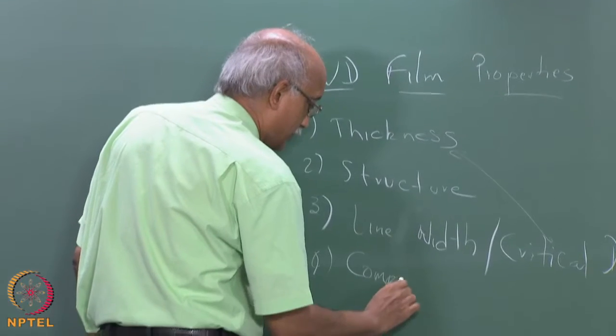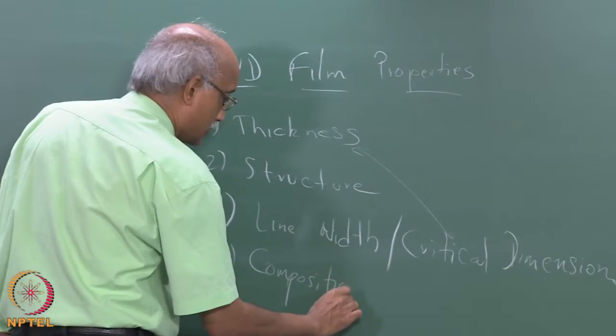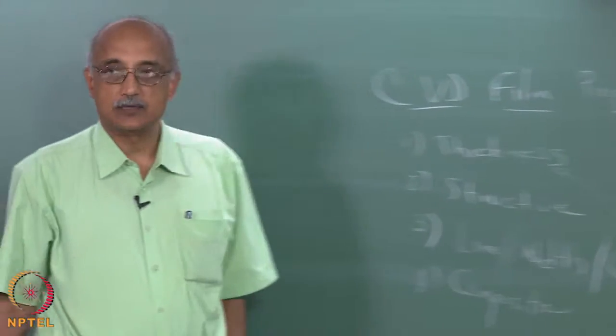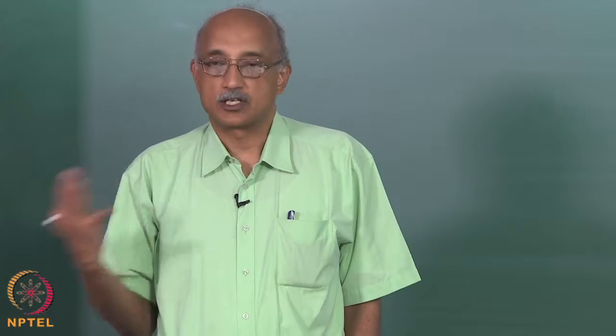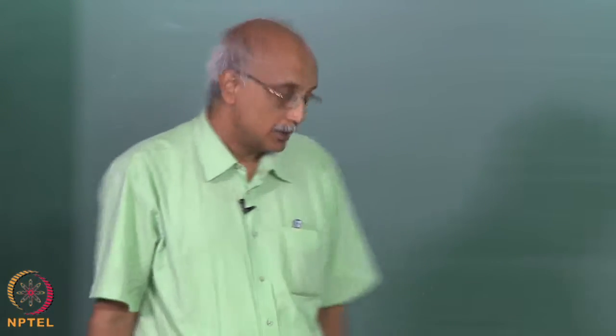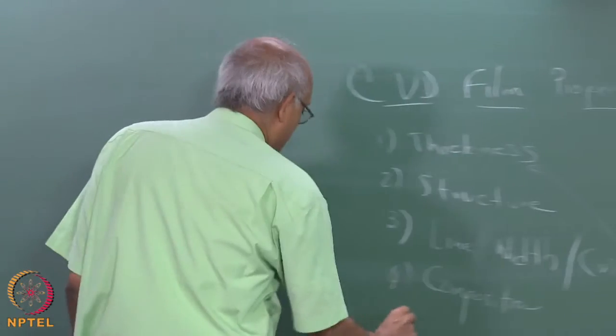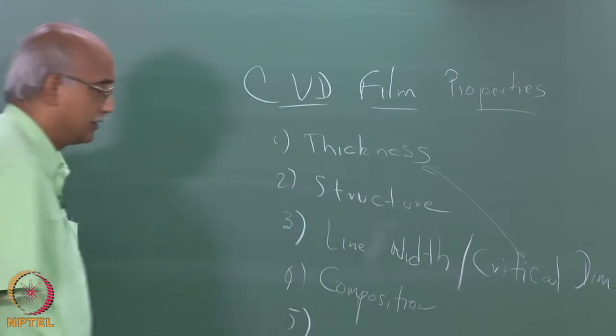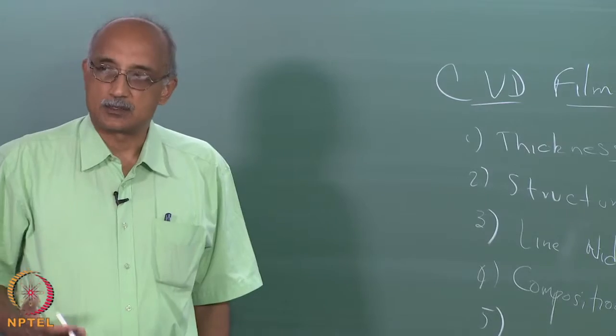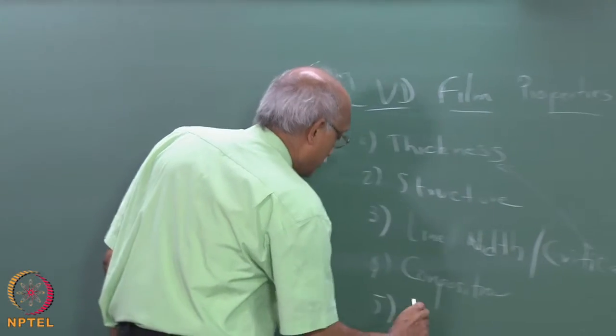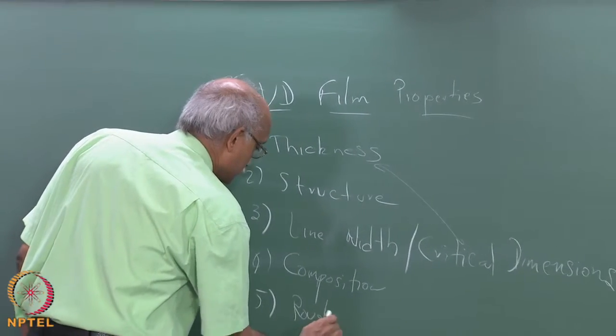Composition is obviously very, very important to know. You are trying to deposit a certain CVD film, you have to be sure that that is what you are depositing and that it is not some non-stoichiometric film that you are depositing or something that is completely different from the chemistry that you are trying to achieve on the substrate. So, the composition is important. And then, you know, the surface properties, particularly roughness, can be a very important parameter to measure.